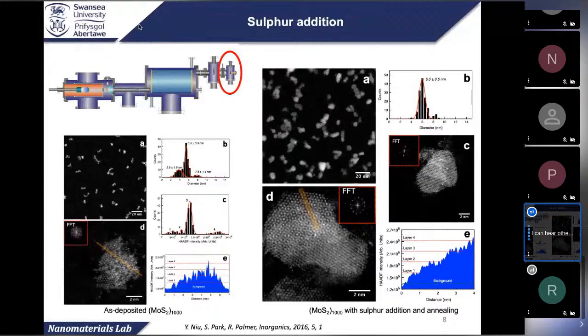So after deposition, we just add extra sulfur onto the cluster. So we made the cluster crystalline, and then we test the activity again. From the left bottom, you can see this is the size-selected cluster after deposition. It has 1,000 units of MoS2, but basically they are polycrystalline. But they have a layered structure, as shown from the STEM line intensity profile.